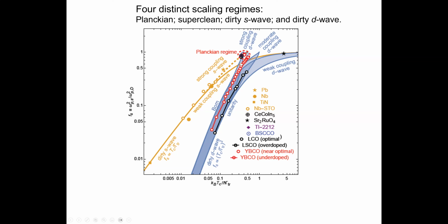So what you see is that all the optimally doped cuprates now cluster in exactly the same area. They are in this little dashed circle, which we call strong coupling D-wave. And because it's dominated by inelastic scattering, we've given it the questionable name of Planckian regime. This is the Planckian regime up here. On the other hand, David and Steve also found a lot of underdoped and overdoped data and plotted it for the first time on the same plot. And what you see is that this dirty D wave line is now being followed, but it ends in another set of points which is dominated by inelastic scattering.